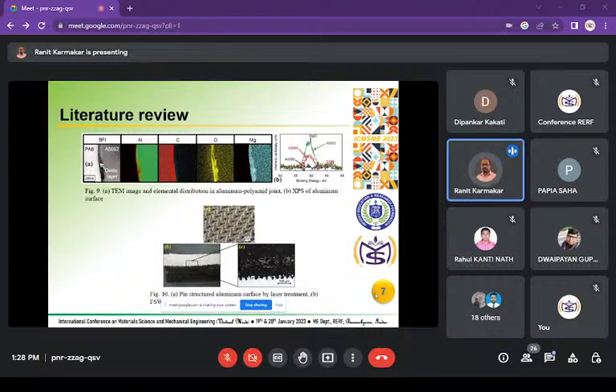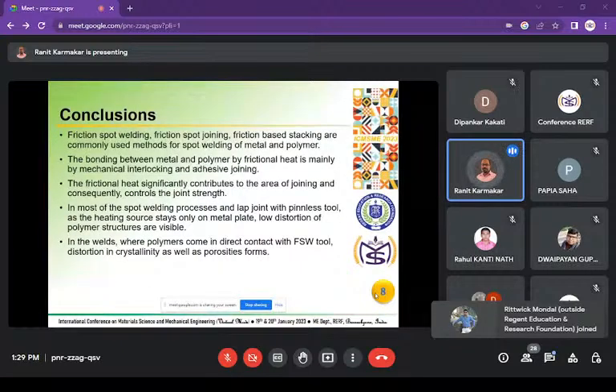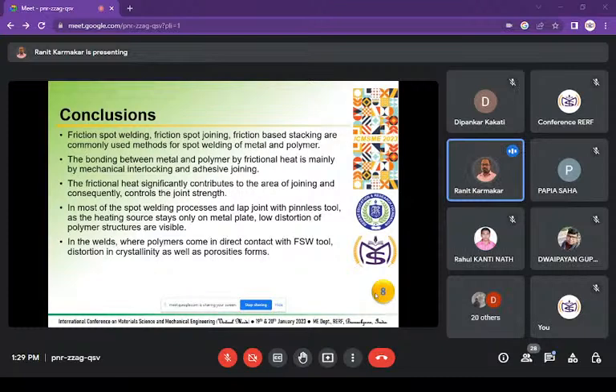In the TEM structure of the metal and polymer, they have shown that aluminum with different alloys is joined at the interface by the oxide, and the oxide is prominent in the EDS maps of the TEM. In another method, they have pin-structured the aluminium surface, and by laser treatment the pins were fabricated in the layer, and by the heat of the friction, the aluminium is adhered to the polymeric structure. And this is the conclusion from our study. Thank you. And this is the reference.